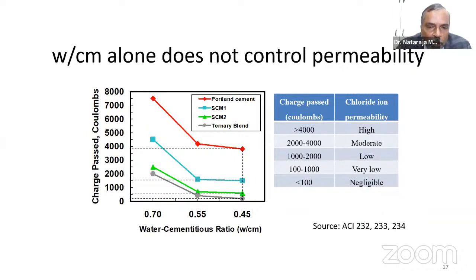So if you want to make your concrete impermeable, you have a concrete, you have a mix design, everything is defined, but replace some 25% of the cement, 50% of the cement, by the supplementary materials, quality supplementary materials, bring it down to a binary blend, ternary blend, and with that, your rapid chloride permeability decreases tremendously, and your concrete has a very low permeability.